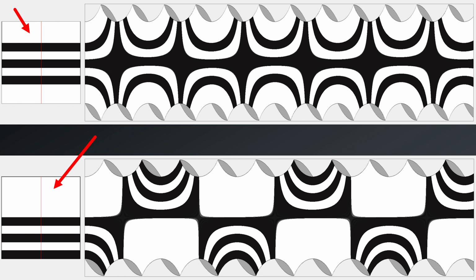You might have already noticed that I started off with the same billet configuration that I used for the chevron pattern. Problem is, it does not produce the correct pattern for the checkers. It is similar, but is not the correct one. The smith used a different arrangement of layers for the checkers. Which one? This one. He stuck to the 3 black layers but shifted them to the bottom of the billet, and the other half was made of a thick white layer. This billet arrangement produces the correct patterns for the checkers as in the original blade.